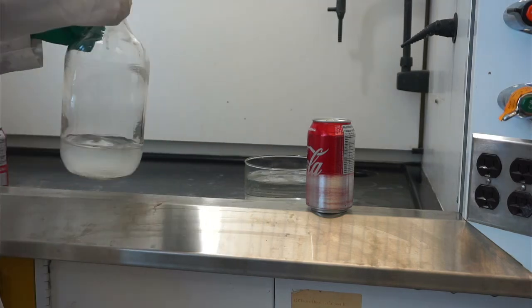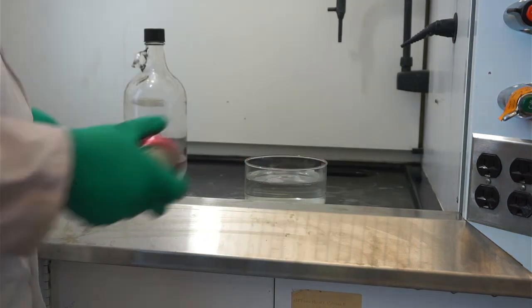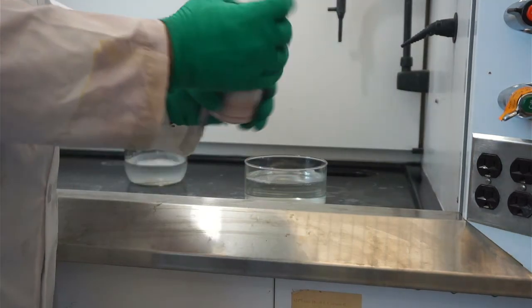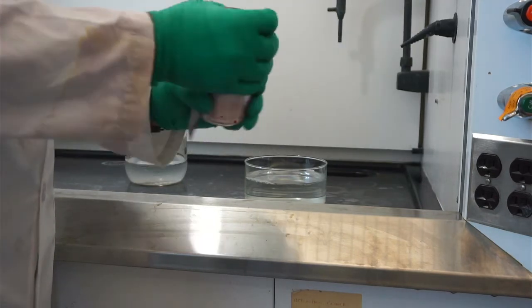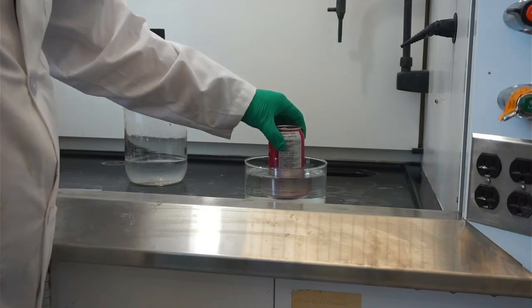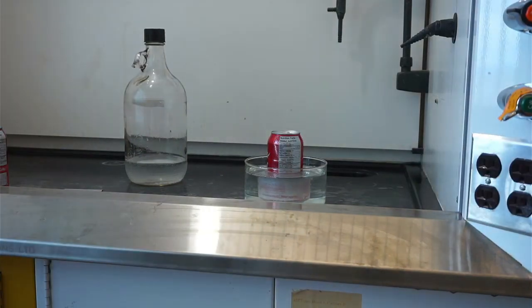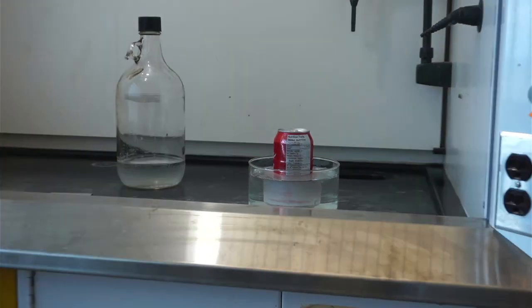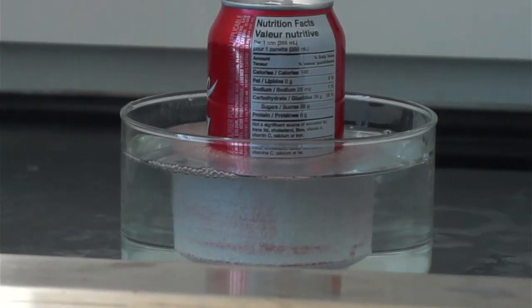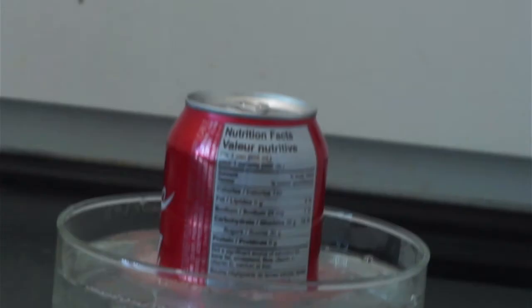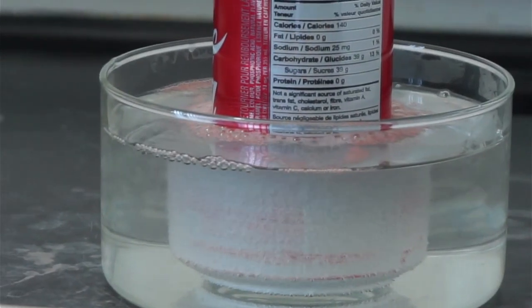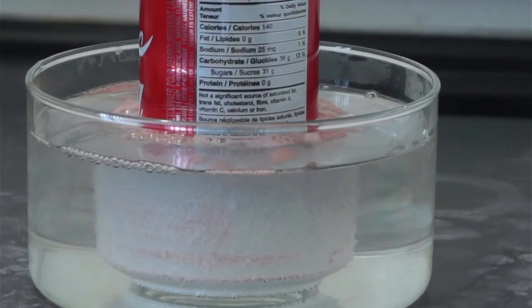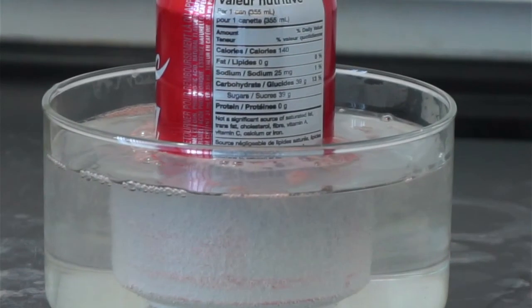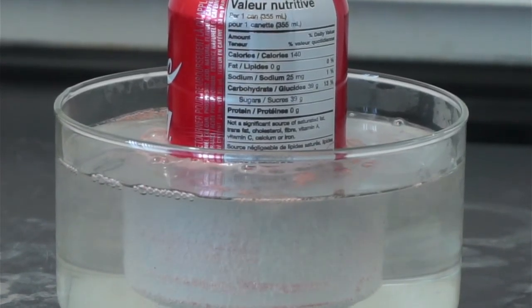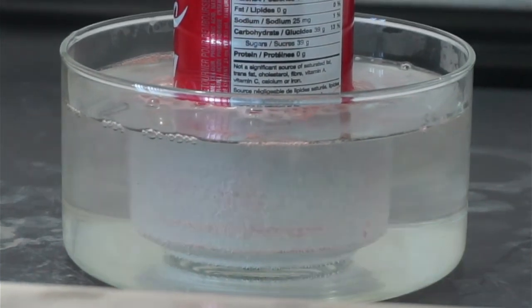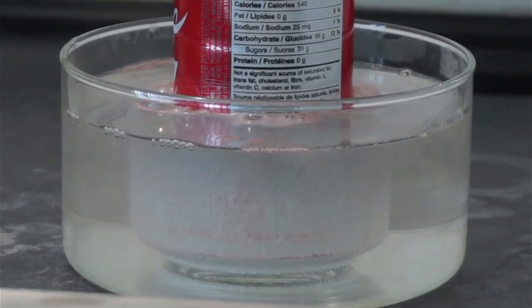So what I have here is a strong basic solution, and I'm just going to remove the oxide layer that's on the outside and put this in. We can then zoom in on it. And I'll even move the camera to try to get closer. And you should be able to see that there is a reasonable reactivity. There's bubbles forming around the aluminum can as the reaction is proceeding. So that reaction is going to slowly eat away at the aluminum, well, much faster than normal.